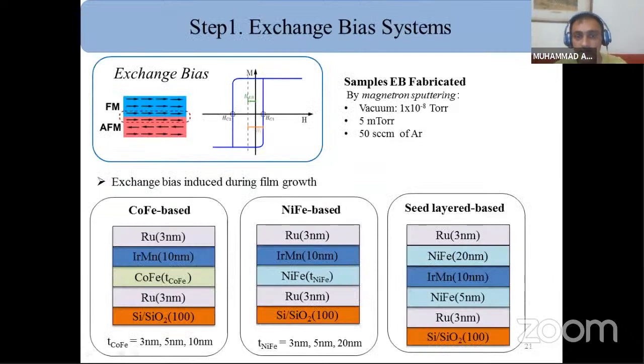Here in step one, I have prepared different exchange bias systems by using magnetron sputtering. Different exchange bias samples were prepared using cobalt iron, nickel iron, and seed layer based systems. By choosing different thicknesses of cobalt iron, we have prepared different exchange bias to be used in a spin valve and magnetic tunnel junctions.